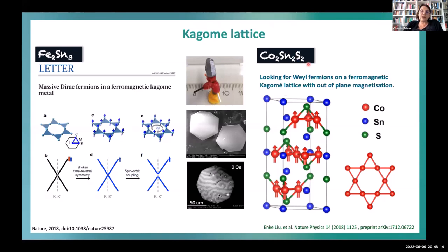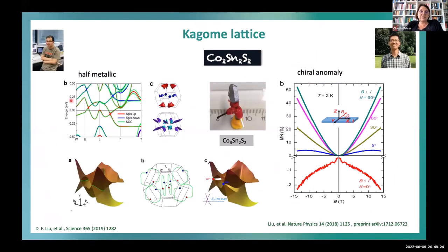In this family, you are also close to a semiconductor. Sorry, I have a typo here. It's a 3. So we are very close to a semiconductor. So it's also a half-metallic ferromagnet with a very simple band structure, as you can see here. It's similar to the Heuslers. You have these crossing points, and only the crossing points close to the Fermi energy.